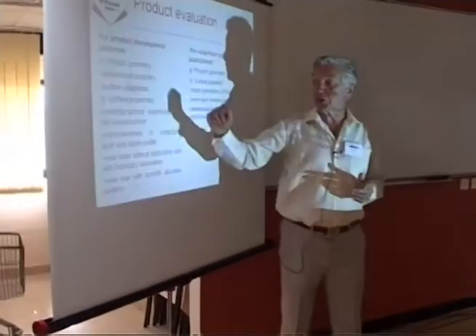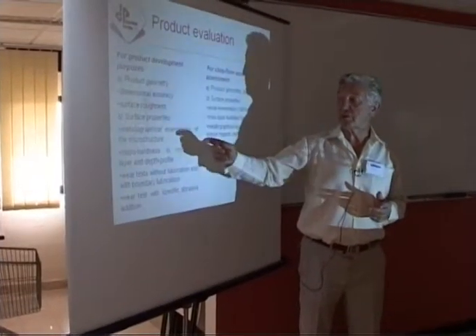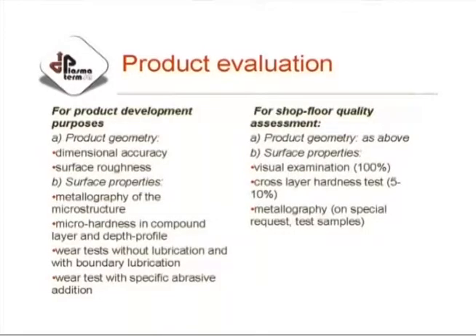So for the development processes, we will test not only product geometry, like dimensional accuracy and surface roughness, but surface properties like metallographical examination of the microstructure, microhardness in the compound layer and the depth profile. And we also perform wear tests without lubrication or with lubrication, boundary lubrication.